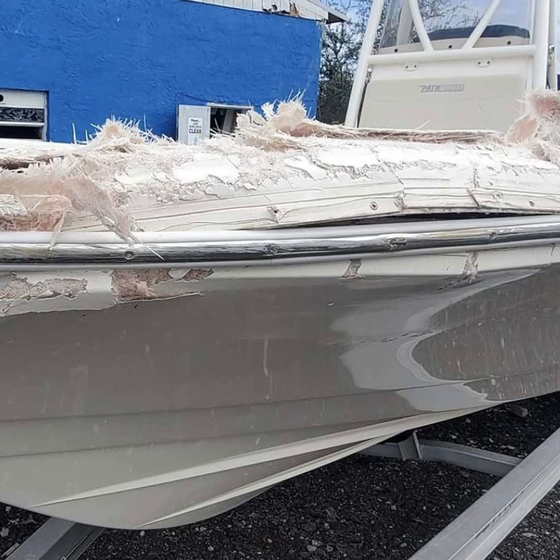So we're talking about how big your repair is going to end up. And a lot of that depends on how thick your fiberglass is. So in this example, we're going to talk about a pure fiberglass laminate that is a 1/4 inch thick. This could be a center console or something like that. If your fiberglass is a 1/4 inch thick and you're going to use a 12-to-1 bevel ratio, that means that you are going to do a 3-inch extended area all the way around the extent of the fiberglass damage.